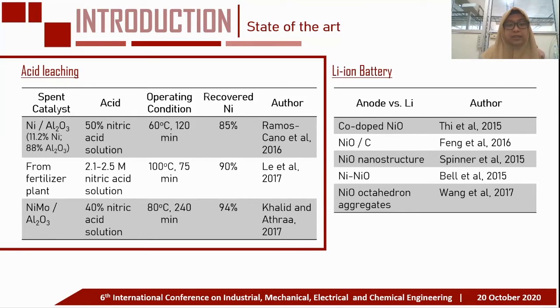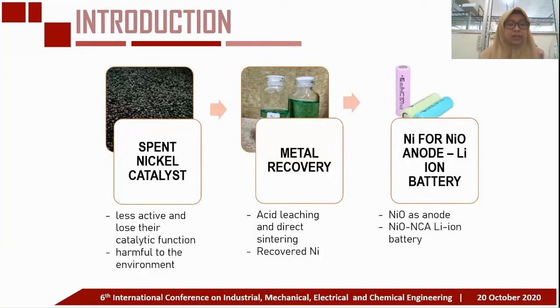There have been many studies on the use of NiO as anode, but NiO derived from spent nickel catalyst doesn't yet exist. Moreover, NiO as anode and nickel cobalt aluminium oxide, or NCA, as cathode have never been done. The electrochemical performance of NCA, which reached 200 mAh per gram, is expected to be a support for NiO NCA batteries. Finally, we have the spent nickel catalyst to be used as battery anode and NCA as cathode.